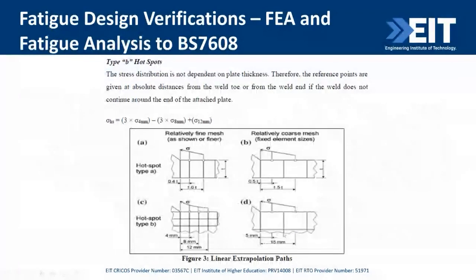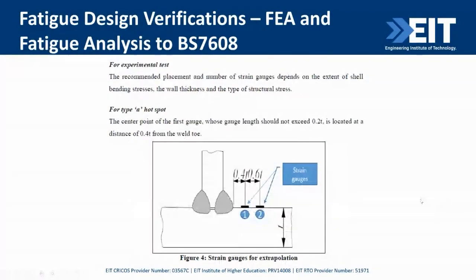The hotspots, I won't go into all this, but the hotspots, as I say, 0.4T and 1T. For hotspot B, there's a different system of this extrapolation. And for coarser meshes, you can do the 0.5T and 1.5T. I find this 0.4T, 1T easier and better, but it's up to you.